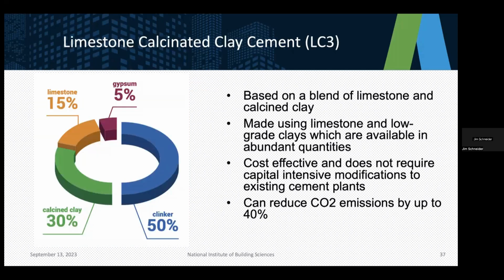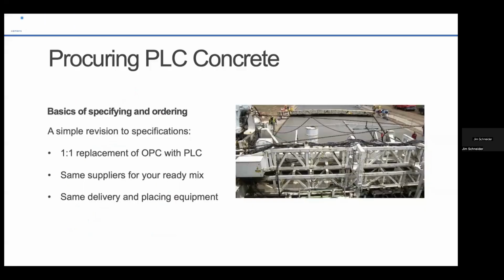There's also limestone calcinated clay cement, or LC3. This is based on a blend of limestone and calcinated clay, made using limestone and low-grade clays, which are available in abundant quantities, and cost-effective, and it doesn't require capital-intensive modifications to existing cement plants. This can reduce CO2 emissions by up to 40%. So again, this is kind of getting used to thinking about mixes in a slightly different way, but there can be some real impact in terms of carbon with LC3 as well. In terms of procuring PLC concrete, it's a simple revision to specifications. It's a 1-to-1 replacement of OPC and PLC, usually the same suppliers for your ready mix or precast. Same delivery, placing equipment.